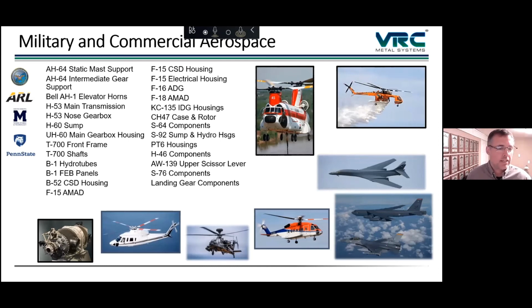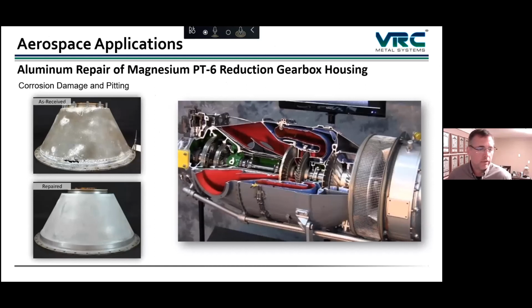And a lot of these were actually aluminum parts, which is very sprayable with the cold spray process. So there's been a lot of repair work done, a lot of different applications for the aerospace community. Just to show you a couple of them, here's one where a magnesium gearbox, this is a reduction gearbox for this PT6 engine. And in this case, the one that was given to us for repair, to qualify the repair, actually had through wall defects. So you see a hole through the part here that was able to be filled in and repaired. So the bottom here, you can see the repaired part.